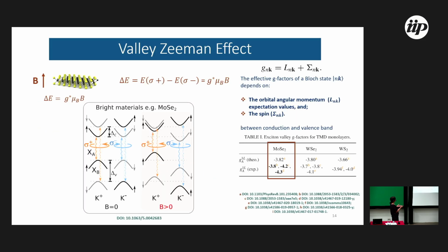And you can measure the valley g-factor. The difference of energy between the valleys is proportional to the magnetic field, and you can extract the g-factors, which we call valley g-factors. It depends on the spin and the orbital angular momentum, and for bright excitons it is around -4. But if you are dealing with dark excitons, it can be -9.